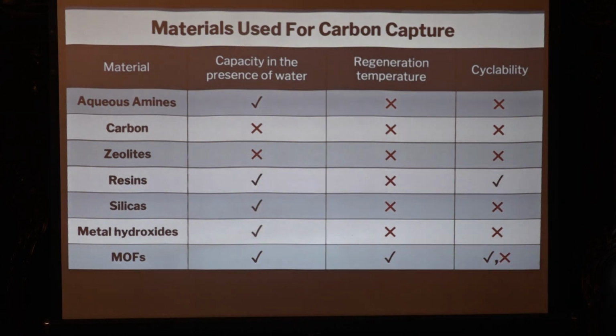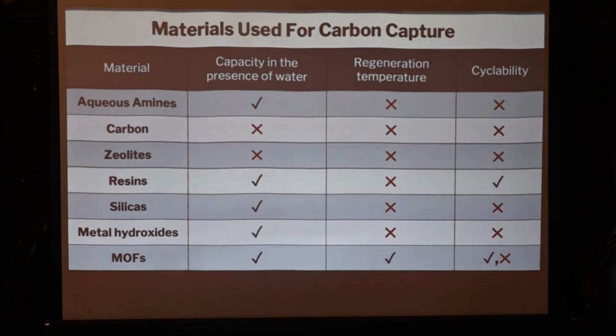For example, aqueous amines, which is an old technology that is now being deployed for CO2 capture, is a problem because these amines are corrosive, they're toxic, and they create their own environmental issues. Carbon zeolite resins, you can see where these things fail. MOFs, as you'll see, it's complicated. The story of MOFs and carbon capture is complicated, as you'll see in a minute. But they are at least the ones that are now at the forefront of CO2 capture from flue gas of cement and petroleum, but not from air.